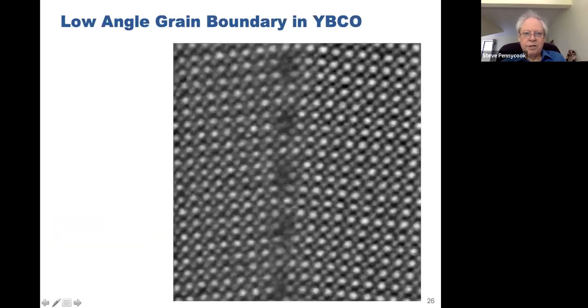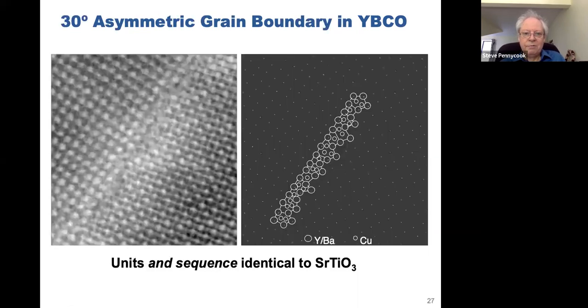Well, I already mentioned high TC superconductors one time. This is actually an image. It looks very like strontium titanate, but it's actually YBCO, grown epitaxially on a strontium titanate bicrystal. The amazing thing, or at least it was amazing at the time, of course, this is derived from the perovskite structure, so maybe it should not be so surprising that the units we saw in these boundaries were actually identical to what we'd seen in strontium titanate. And that was true not only for those symmetric boundaries, also for asymmetric boundaries. The units and the structural sequence identical to strontium titanate.